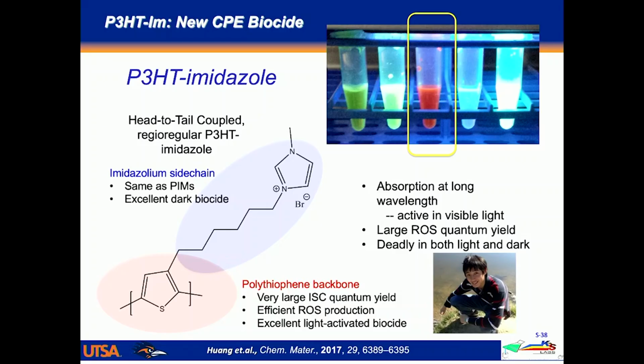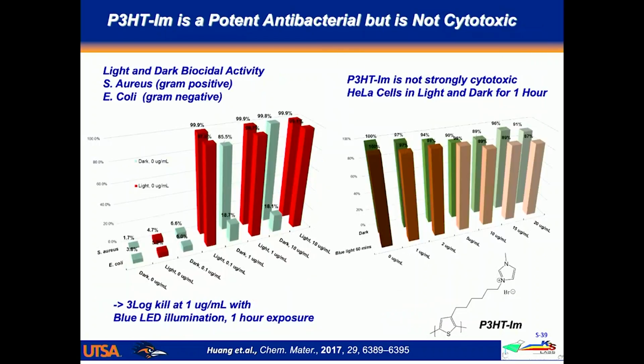And we think it has to do with two things. One, this polyelectrolyte is very hydrophobic, so it really interacts quite strongly with the membrane of the bacteria. But in addition, polythiophene has a pretty high triplet yield, so it's quite effective at generating reactive oxygen species, which we believe are the cytotoxic element that's produced on light exposure.